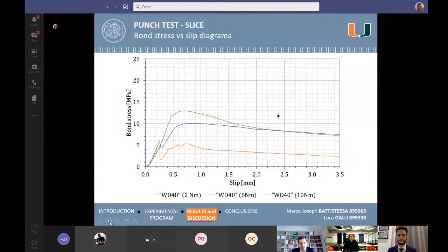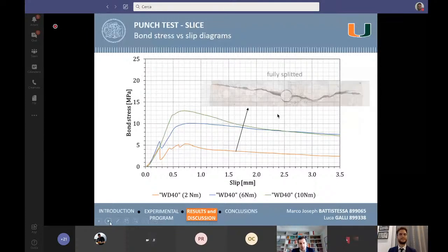This bond stress versus slip diagram points out the three typical results that we have observed during all the punch tests performed. In fact, no matter the kind of support configuration we use, similar trends have been obtained depending on the occurrence or not of the splitting phenomenon in the concrete slices. The orange curve is an example of trend that we have obtained in all the slices recorded as fully splitted. As you can see from the picture, those specimens were characterized by a fully developed crack.